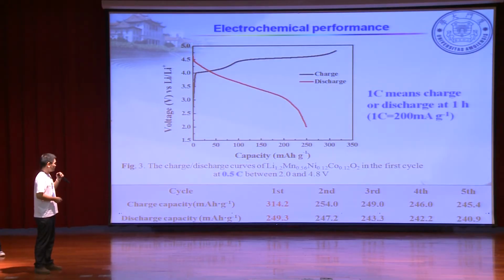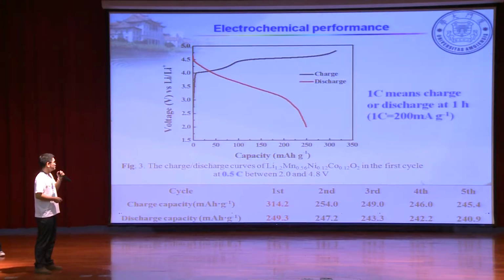Then we test the electrochemical performance. Our designed product has very high initial charge capacity, and it could be 314.2 milliampere-hour per gram. And the reversible discharge capacity is 249.3 milliampere-hour per gram, which is about 80% of the initial charge capacity. And in the first 5 cycles, there is a little capacity loss, which suggests the good cyclability.